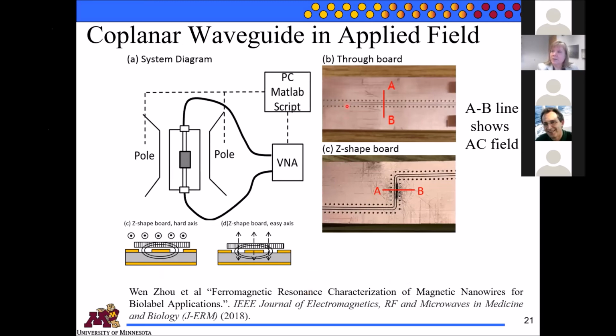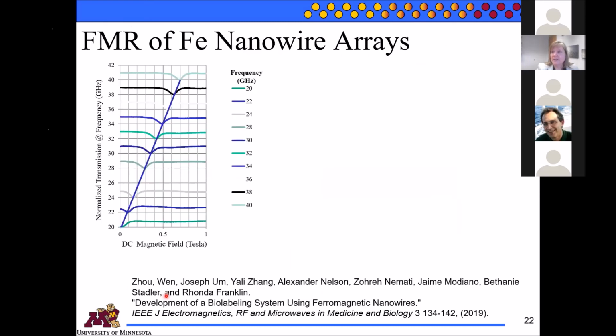And we varied the way we make our coplanar waveguides. With my colleague, Rhonda Franklin, and her student, who first authored this paper, we were measuring the FMR of our samples. And this is that Kittel equation. Like I said, if you sweep the DC magnetic field, you find that the frequency of resonance is going to shift. So here are the different frequencies we're applying and the DC fields at which there was a resonance.